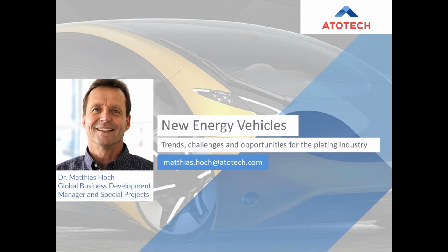And what is very important, you need a good brake and even an oversized brake for emergency brakes. So we cannot avoid the brakes, because we never know if deer or people or children or whatever is running in front of our cars. Then we have to do an emergency braking, and for this we need a very, very strong brake. And therefore, it's also so important to think about the brake pads and the backing plates, that they do not corrode, because the brakes are used much less. So if corrosion can develop, then probably the function of the brakes is lower than in a normal system, which is in use all the time. So we have to keep the brakes functioning in an almost brand new state, and this is only possible when we have non-corrosion in our brakes.